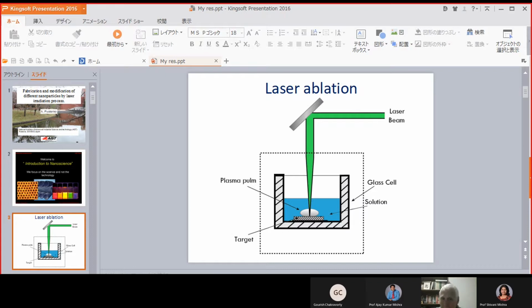Reduction is the first, but next, on the surface of these nanoparticles, citrate coats the surface and prevents the final nanoparticles from further aggregation. Without this surface prevention agent, the agglomeration process continues and continues. So we would produce a huge piece of silver, not nanoparticles. Nanoparticles would continue to aggregate, so our result would not be so beautiful, a bad result.